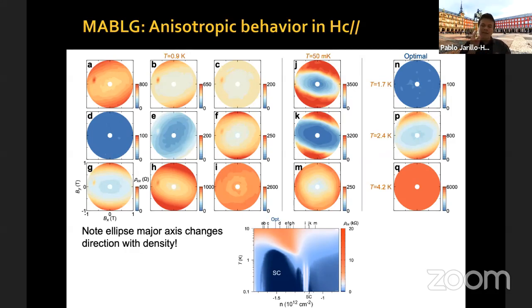And in particular, what that is telling you is that it is hard for this nematicity to be directly related to or originate mostly from, for example, a uniaxial strain which is very strong in your sample, okay? Because if it was a mechanical structural strain established in your sample, that would not be so dependent on small doping density, okay? So the fact that this nematicity director can rotate is a strong indication that something else is going on, and that this nematicity is most likely of electronic origin.